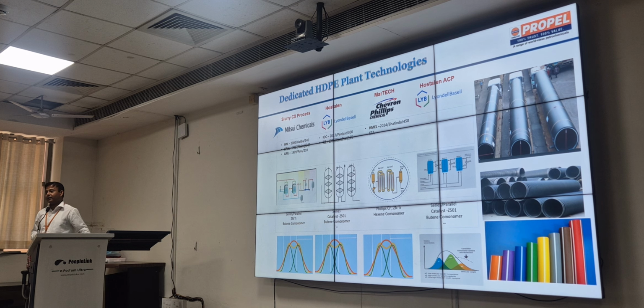This is the Hostalen ACP, advanced cascade process, as compared to the Hostalen conventional. In this, you can produce much higher molecular weight products, multimodal products for applications where you require. But the challenge is that you can produce the high molecular weight in the same reactor, but it will not be suitable for processing. You can produce whatever high molecular weight you want in the one reactor or two reactor system, but you will not be able to process at the machine level. So that is why this technology has played an important role for multimodal molecular weight distributions, which create the processability window and also create the high molecular weight in terms of performance.